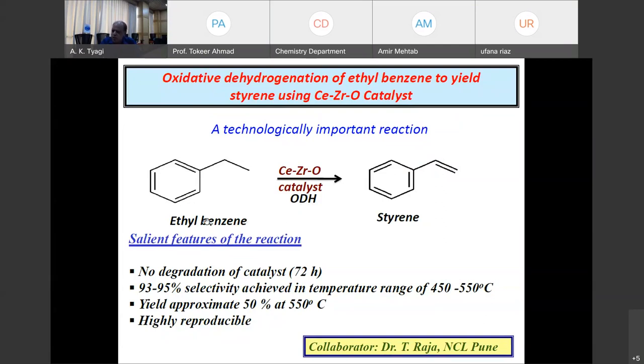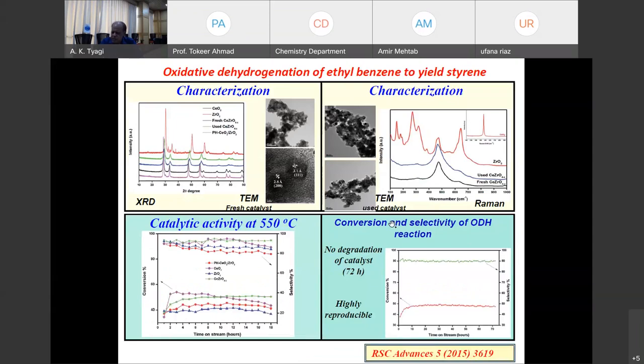And styrene is very important. Ethylbenzene is very cheap. Styrene has high value. It is a monomer to make polystyrene. So you see, simple solid state chemistry could be used by our friends in NCL Pune. Some catalysts were characterized before and after performing a long-term reaction. As I mentioned, this is a very stable system. For about 3 days continuously, if you perform conversion of ethylbenzene to styrene, it does not break. That is the beauty of crystallographically designed nanomaterials, the main theme of my today's talk.